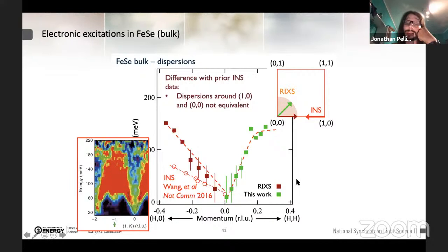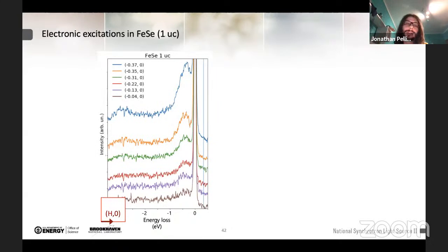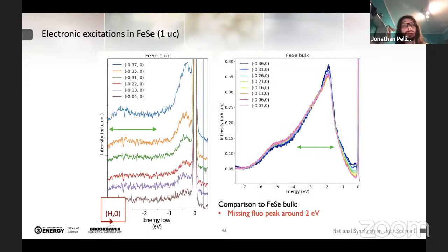But now the next step is to measure the RIXS spectra on iron selenium monolayer. And here I'm showing on this plot the RIXS spectra at different momentum points along the H0 direction for the monolayer case. This is pretty different from what we observed in the bulk case.